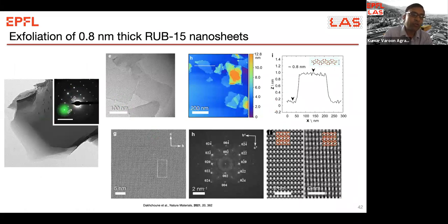Essentially, you go through a hydrothermal process to make these layers. So this is quite a standard way of making layered zeolites. And then we have this method of exfoliating these layers, going through swelling of these layers to reduce the interlayer spacing, and then a polymer shearing process where we can form very uniform layers, which are just a unit cell thick, right?